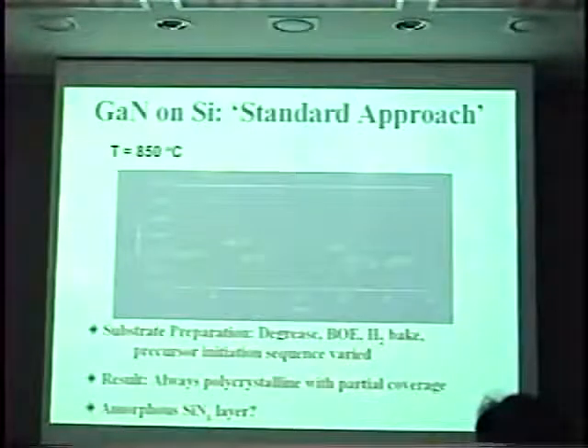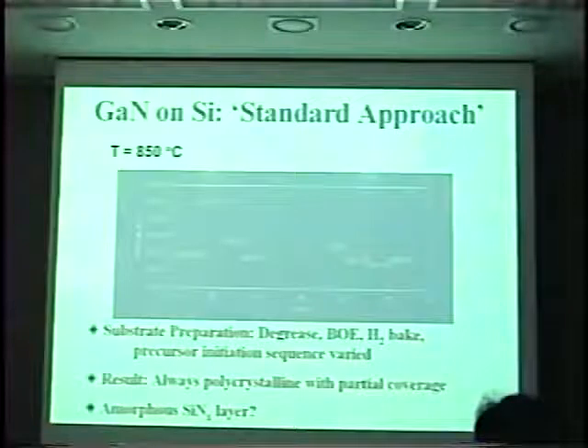So we took our standard approach. We tend to use a little bit lower temperature on our growth than typical, but our standard approach for doing gallium nitride on some other substrates was to grow using triethylgallium and ammonia at 850 degrees centigrade. When we did that, you can see we get polycrystalline gallium nitride. Not very good quality at all. It always resulted in polycrystalline material, only partially covered. We suspected that because we did a nice standard etch on silicon prep, we had a silicon nitride layer forming.